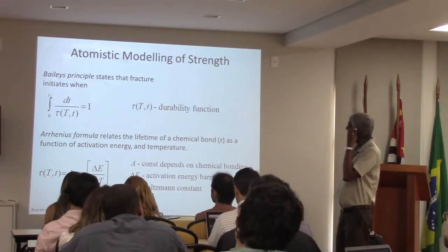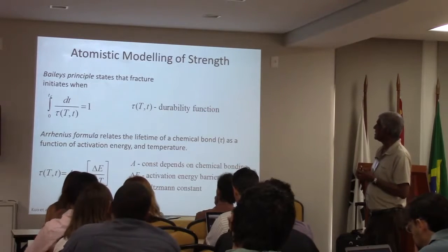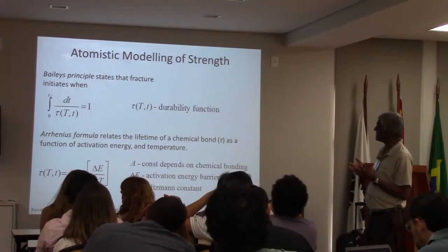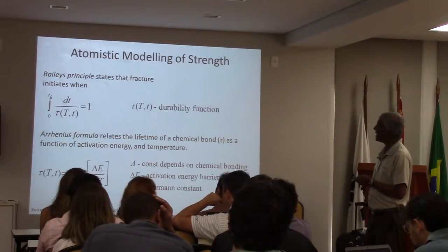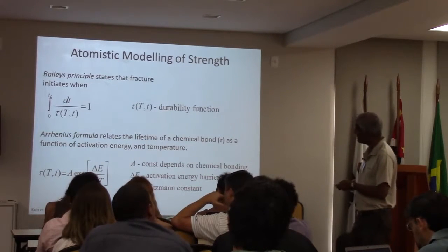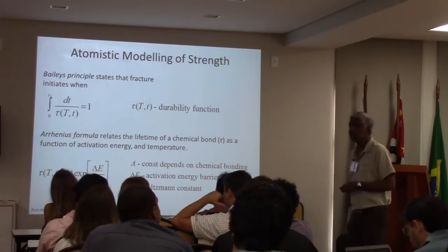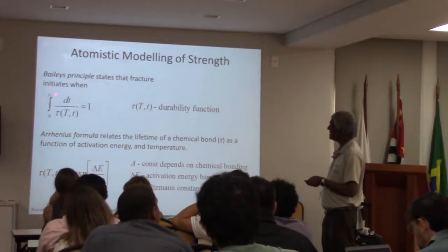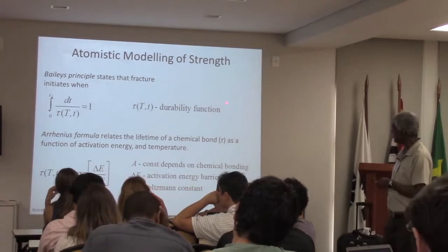Now, that's the MD simulation. As I said, we do have the software and everything to do this. But our idea is, can we get something similar or closer to this using a different model? So here we are using a continuum idea, which is Bailey's principle. It says that the failure of a material can be expressed by an equation like this, which involves a durability function. The durability function you can determine experimentally, and t_f is the time to failure. So it has temperature and time, and this function is determined experimentally.